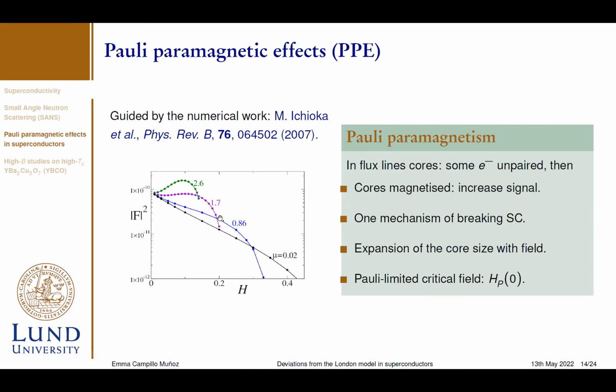However, when the paramagnetic effects present in the sample are negligible, the form factor comes back and behaves as the London model expression. So we arrive at several conclusions from these numerical calculations. One is that we have to base our model on the London model itself, also including this Gaussian cutoff. And when we have unpaired electrons in the cores, the magnetization is increased, and it also ends up breaking the superconductivity. As a consequence of this increased magnetization, we also have an expansion of the core size with increasing field.